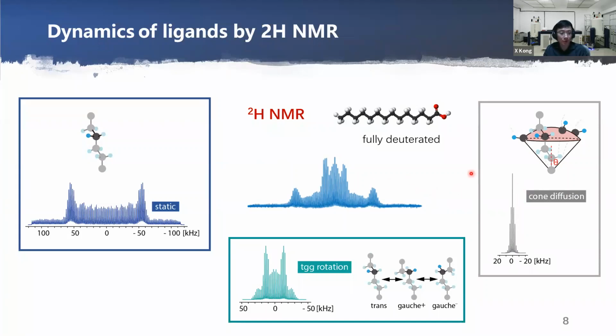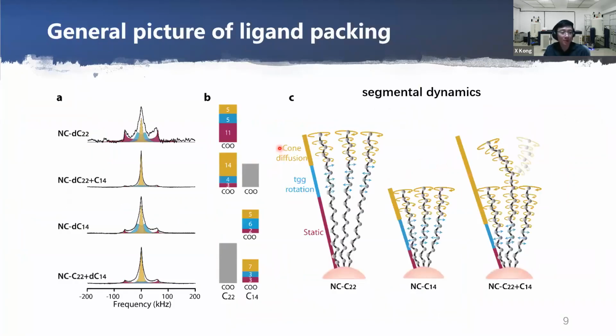So we can get three contributions, and then we perform this deuterium NMR on different samples, either with pure ligands or nanocrystals with mixed ligands. The mixed ligand crystals consist of ligands that are partly long and partly short aliphatic chains, like one with 22 carbon units or the one with 14 carbon units. So either the long ligand or the short ligand can be deuterated for NMR investigation.